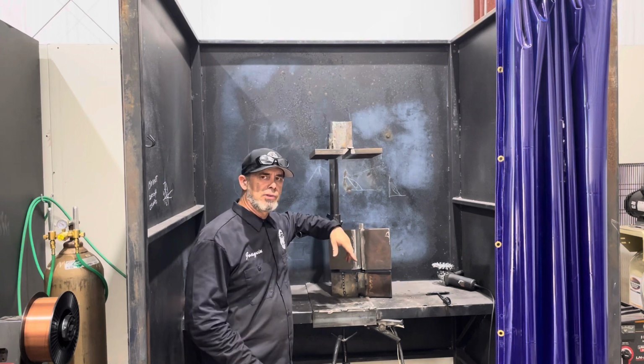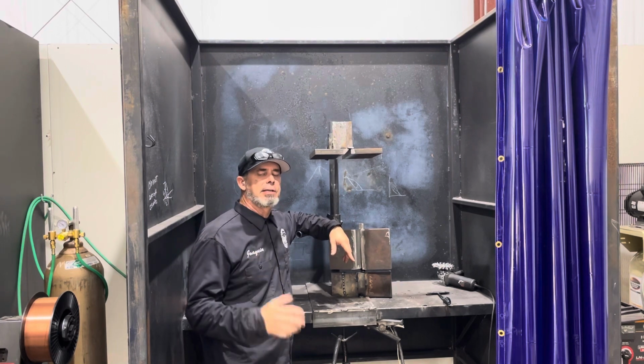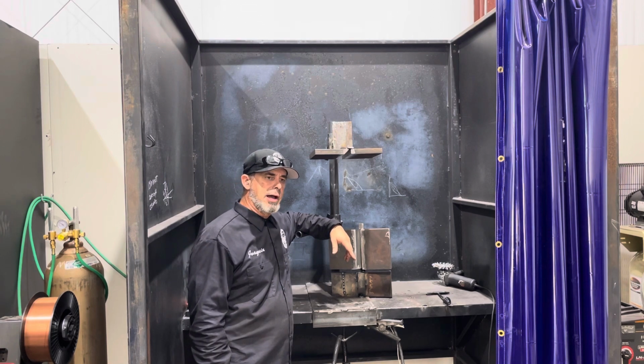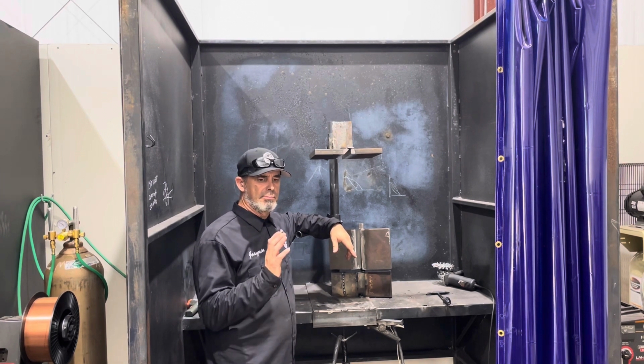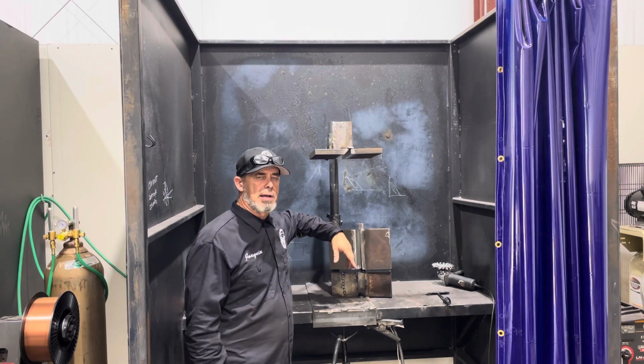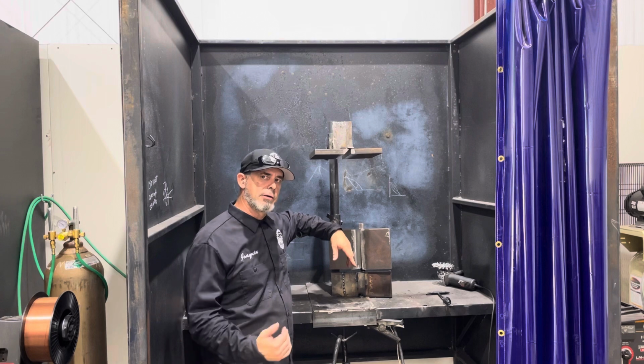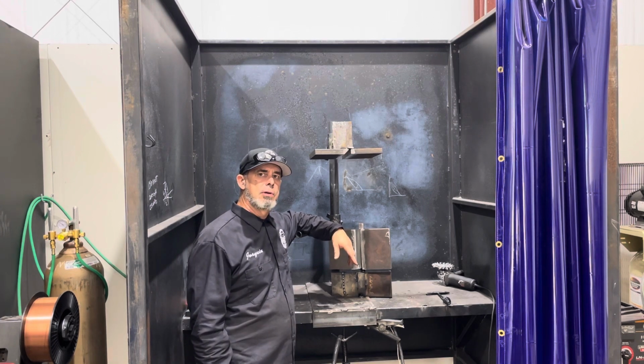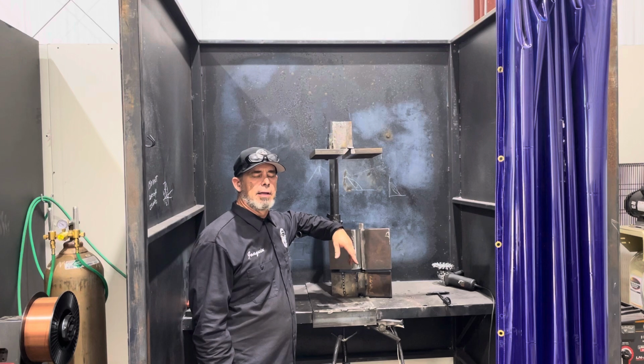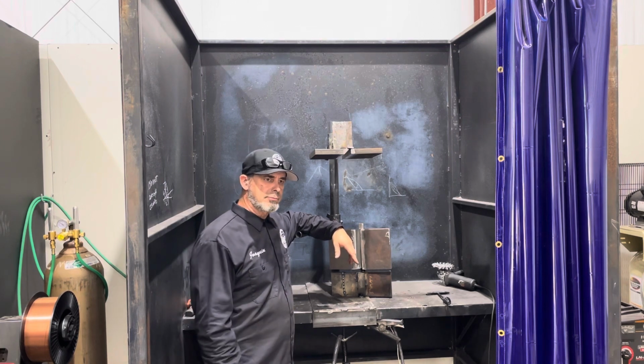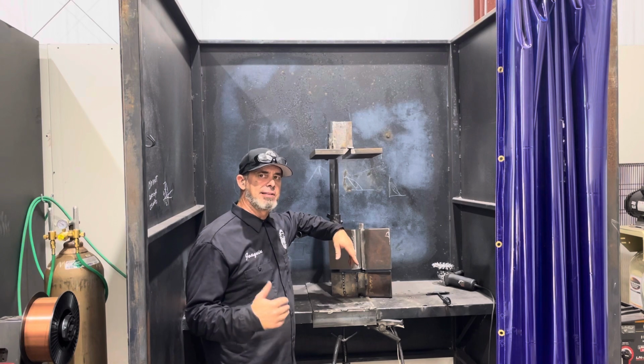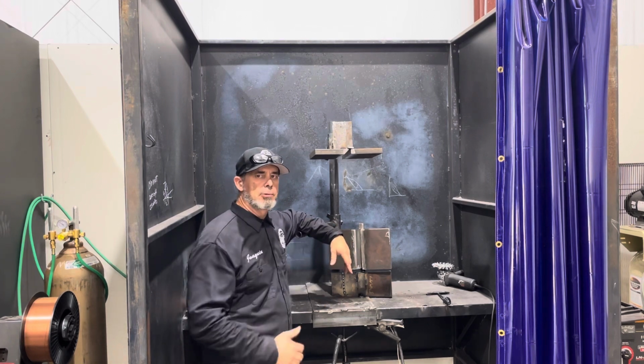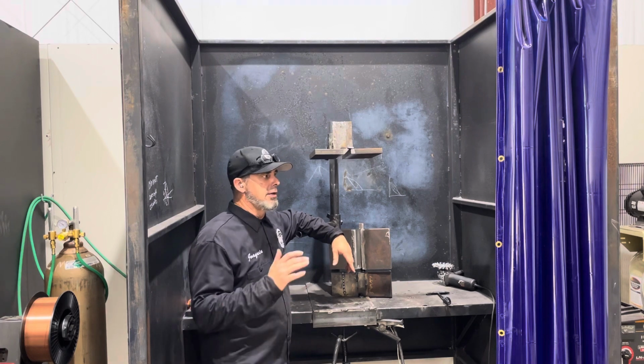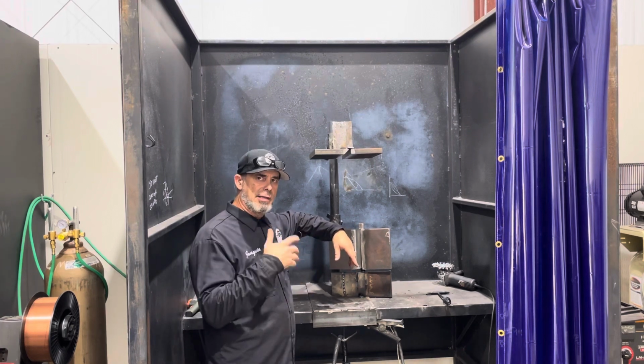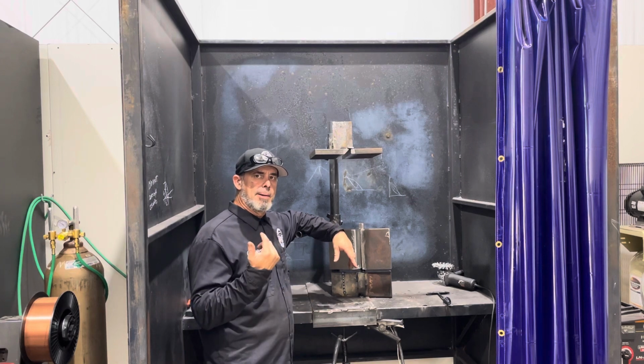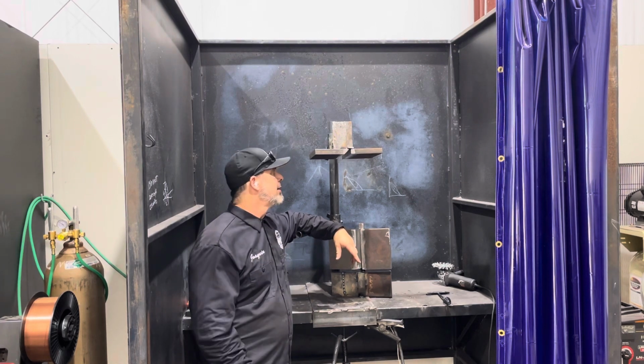Now this material is known as ASTM 514. It's actually a higher tensile strength, between 80 and 100 KSI. So it's some strong stuff. The wire that we're using is Fabco 803, and 803 is known as an 8,000 wire. So that wire is basically 80,000, 90,000 PSI, also matching pretty close to the strength of the material that we're welding out. 514 has different grades. This grade is specified as a grade that is 100,000 PSI.